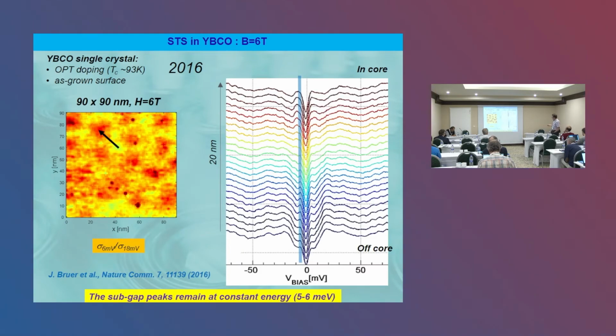Until more recent measurements, also performed on YBCO, where the evolution of the spectra was taken from the inside of the core to the outside of the core, so far from the core center, and where these low energy states, these subgap states, were detected at almost constant position and amplitude. So also outside the vortex core.